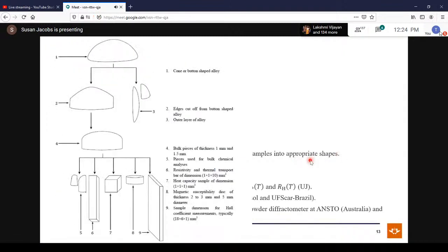Okay, so what are the appropriate shapes? We start off with an alloy button like that, and then we use spark erosion and cut the edges. Resistivity measurements are based on Ohm's law, and you need a uniform electric field across the sample. You also need a uniform cross-sectional area and a length which is much greater than the cross-sectional area. So the ideal shape would be a rectangular bar. And this is the same shape that we use for thermal transport measurements, where you have a temperature gradient across the sample, which gives a voltage, the Seebeck effect. So for electrical resistivity and thermal transport measurements, we use a rectangular bar.